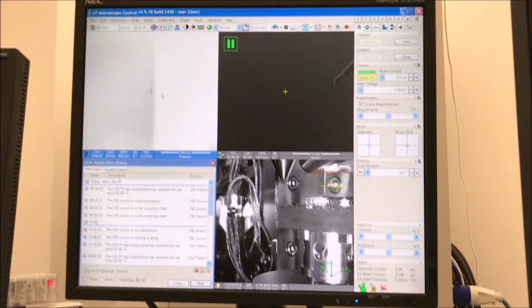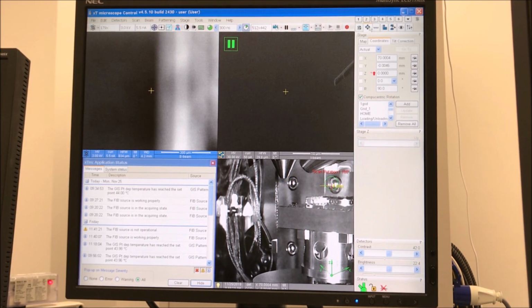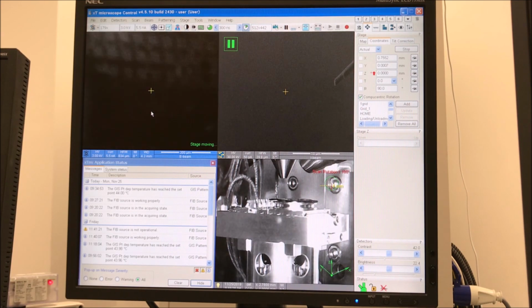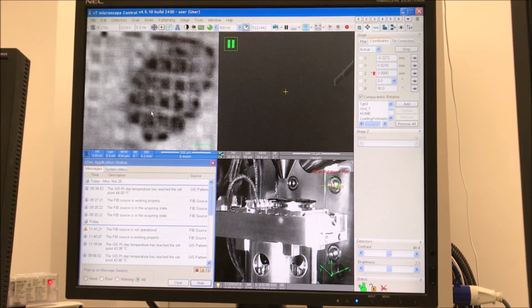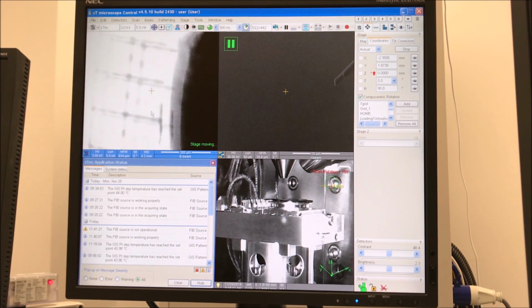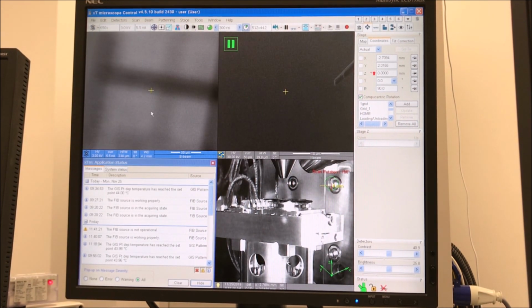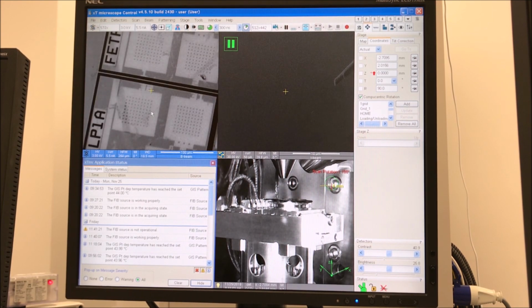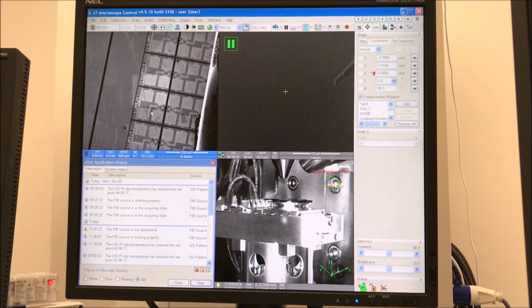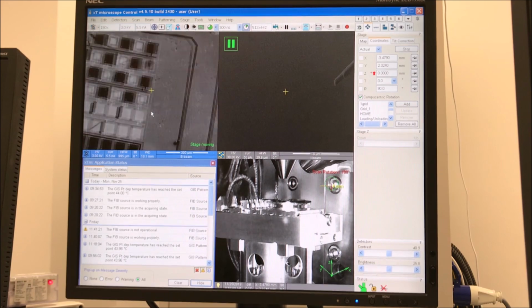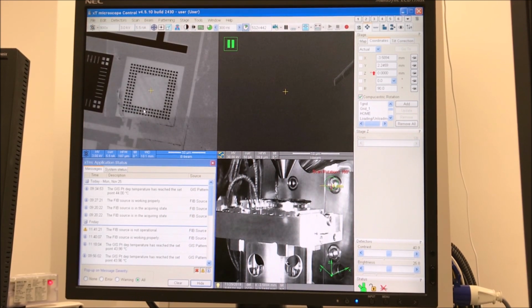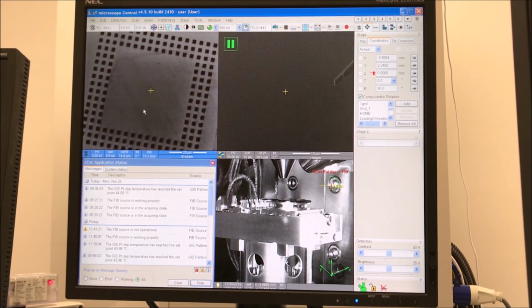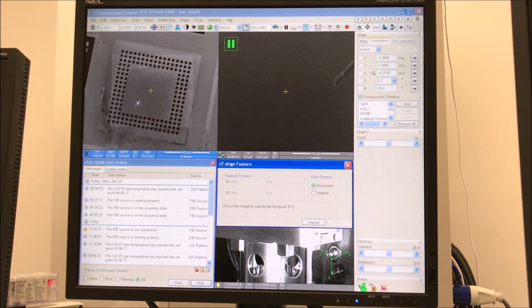Alright, so beams are on, platinum is hot, ion source is on. I unpaused my electron beam. I'm navigating to an area of interest. My electron beam settings right now are 3 kilovolts and 5.5 nanoamps, which I'm going to use eventually to put down electron beam platinum. So right now I'm navigating around. I'm going to make a lamella inside one of these square pads that you're seeing in the E-beam quad.